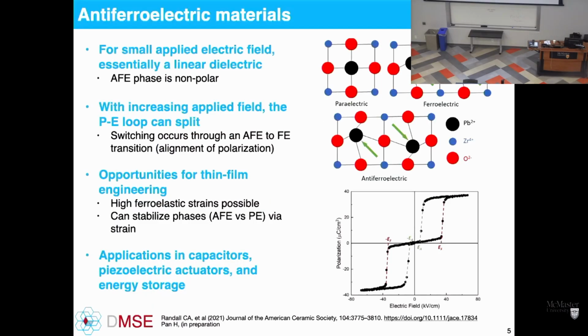But antiferroelectrics are quite a bit different than this. In an antiferroelectric material, rather than a ferroelectric where all your dipole moments are aligned along the same direction, within the unit cell the dipole moments cancel out. Half are pointing in one direction, the other half are pointing in the other. I mean, you have net zero polarization. It has a center of inversion symmetry, and so that is not a ferroelectric, does not support a built-in polarization. But what happens when you apply an electric field to that sample?